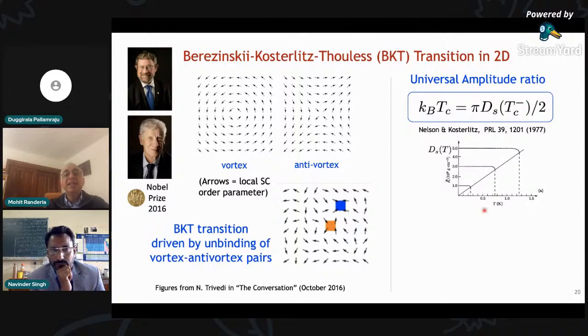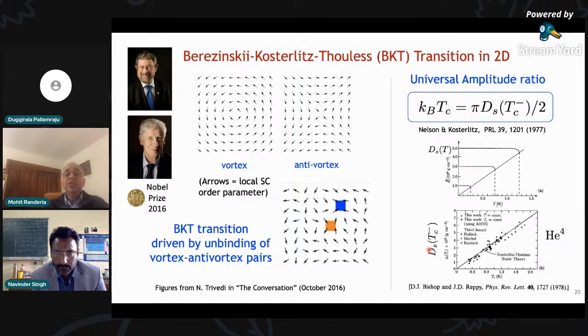at Tc minus. So if you plot the superfluid stiffness versus temperature, then it decreases, and then right at the transition is the value of the superfluid density or stiffness that satisfies this condition. So the higher the superfluid stiffness, the higher the Tc. And actually, this was seen in measurements of helium-4 by Bishop and Reppy, and in 2D superconductors too.